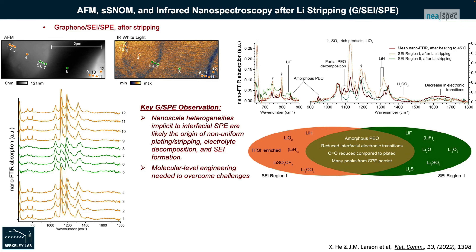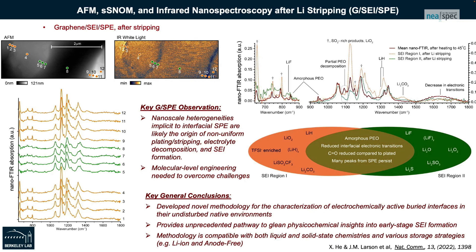We found that nanoscale heterogeneities implicit to the interfacial solid polymer electrolyte are likely the origin of non-uniform plating and stripping, electrolyte decomposition, and SEI formation. Molecular level engineering is needed to overcome these challenges if solid polymer batteries are to be commercially viable in the future. A methodology was developed that can characterize electrochemically active buried interfaces within their undisturbed native environments, and it is amenable to a whole host of other chemistries and battery storage strategies. We hope to use this technique much more in the future. Thanks to my collaborators, funding sources, and for your attention.